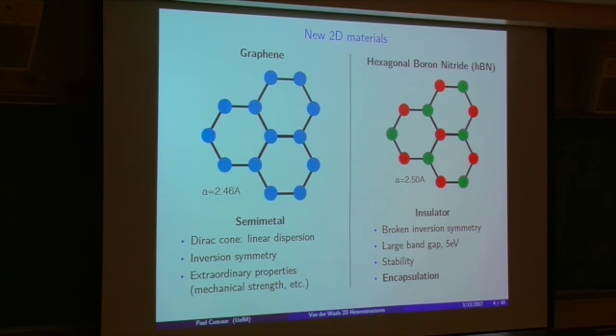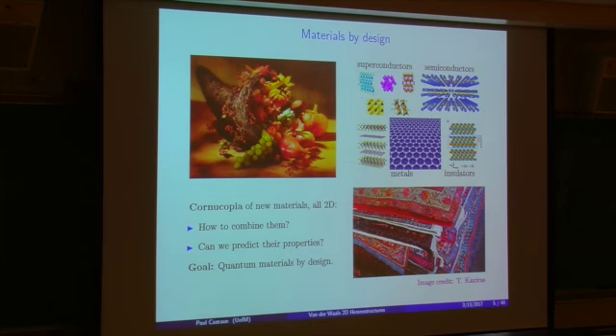So in particular, we know that hexagonal boron nitride is actually a very good insulator, a dielectric. It's very stable. So what we can do, if we want to probe what graphene does and protect it from the environment, is stick it in a sandwich of boron nitride. And this way, because boron nitride doesn't do very much, our layer of graphene is kind of isolated, and we will be able to study it as if it were freestanding, in some sense.